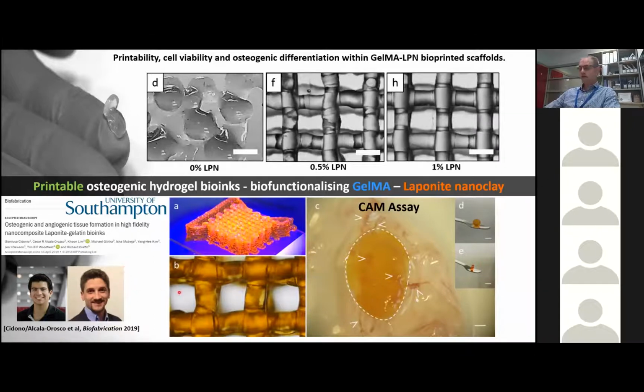One of the other things we would potentially like to do is add a third function, whereby whatever our additive is may also be able to recruit or sequester different types of growth factors. This was some work we did with Richard Oreffo's group at the University of Southampton. They've been working with the development of different laponite nanoclays. Laponite is a disc-shaped nanoparticle with a positive rim charge and a highly negative surface charge, and can be used to make a number of different colloidal suspensions. We were curious to know whether it would have a similar rheology modifying capability for the development of a GelMA laponite nanoclay. It's also a potent osteogenic differentiator, as well as having growth factor binding capability.